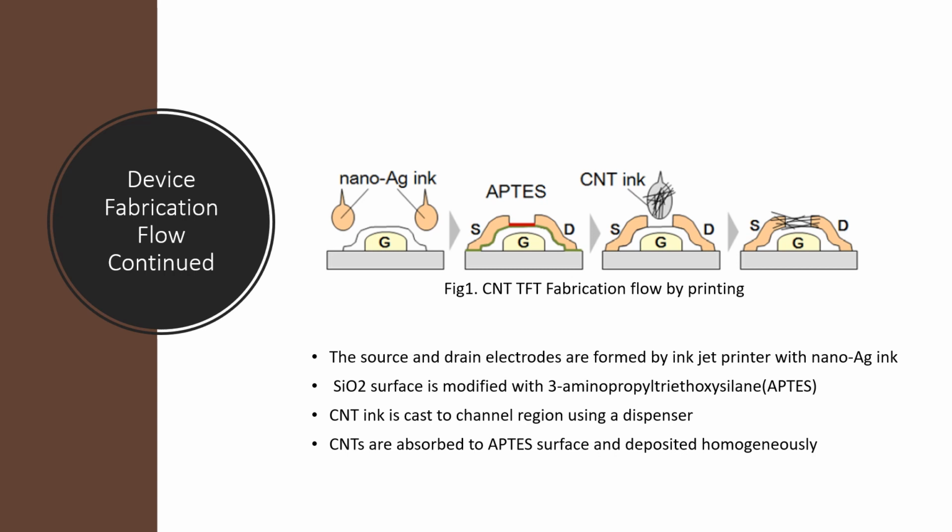In the drying droplet, the micelles containing the CNTs were absorbed to the APTES modified surface, and the CNTs could be deposited homogeneously even in the presence of the outward capillary flow.